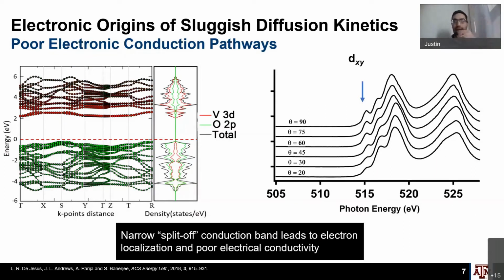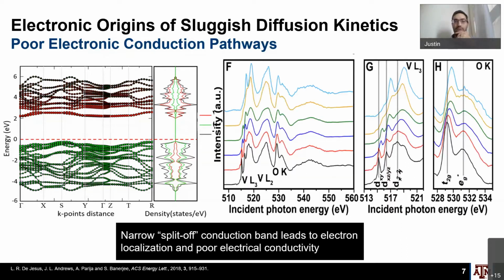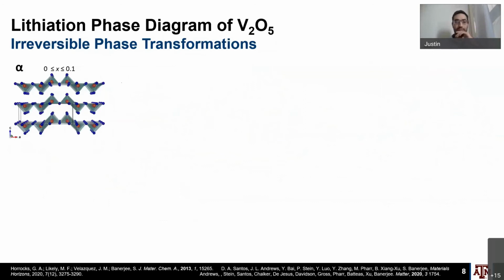And so we've worked a lot in the past at really trying to understand, can we track the extent of lithiation of this material, and we've primarily used the vanadium L edge and the oxygen K edge because, as I'm going to be talking about in a little bit, STXM played a large part, and so those were edges that we could access in the microscopy. And so we have a really good understanding from the spectroscopy of what happens to the X-ray absorption spectra as we lithiate these materials, and so we know where the dxy orbitals are based on the angle dependence of this peak that we see, and then we also know how these features evolve as a function of lithiation, and so this is going to be critical to some of the things I'll talk about in a little bit.